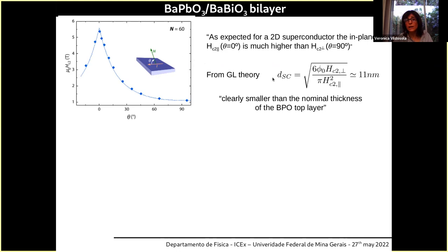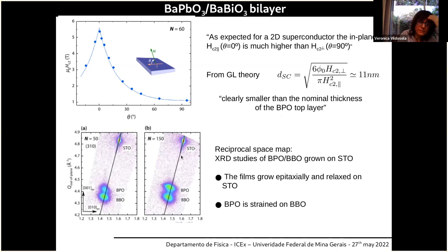And from Ginzburg-Landau theory, they estimated the width of this superconducting phase to be around 11 nanometers, which was much lower than the nominal thickness of the BPO layer on top. And then they provided some structural information that was useful for us to do the calculations later. They observe that the films grow epitaxially and relax on top of STO, and that BPO was strained on BBO.